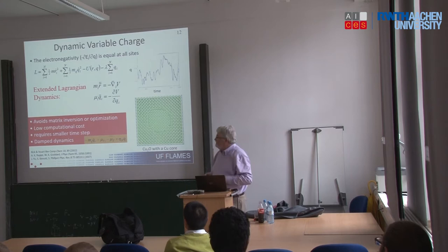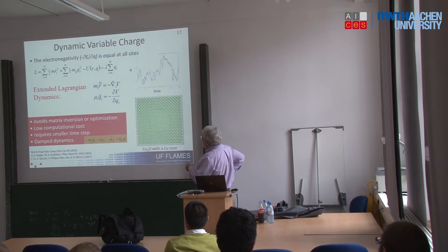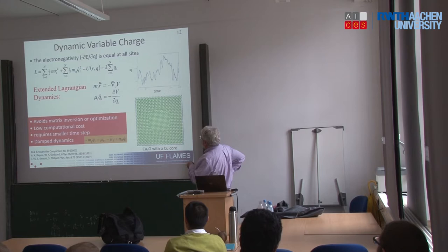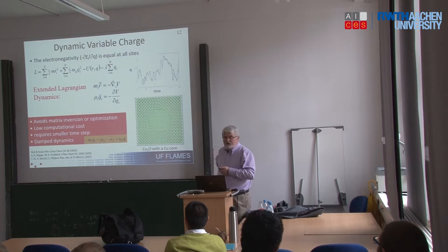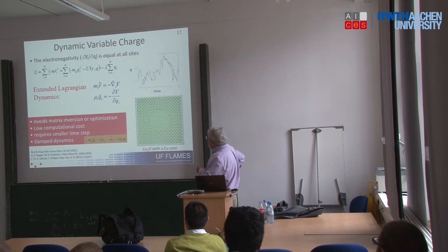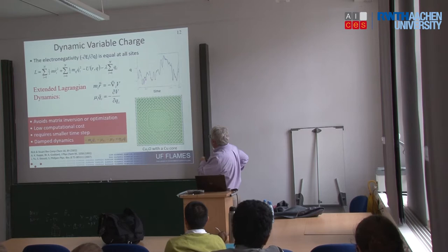So here's an example. Here's the Lagrangian written down. This is the real half mv squared velocity. Here's this fictional charge velocity. Here's the potential charge. And here is the Lagrange multiplier, which fixes the charge. So those who've taken the classical mechanics class, probably most of you have, you'll see something like this, and then we get these two equations of motion, and you integrate that, and you find that for a given atom, the value of the charge is fluctuating, which is what you would expect.